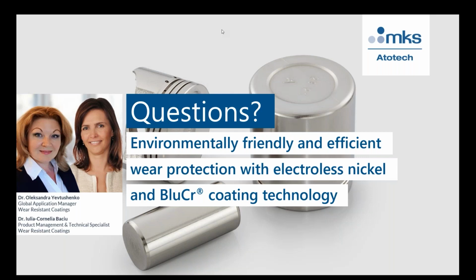And maybe let me make a very short comment on Julia's answer also. What happens with corrosion protection for BluCr during heat treatment? Again, it depends on the nickel. This will be the case as Julia already explained. If you apply Electroless nickel or electrolytic nickel coatings, very important is also the ductility, because if the cracks become wider in BluCr, the nickel layer underneath needs to resist that and to build up the stress without cracking. Yeah, thank you.